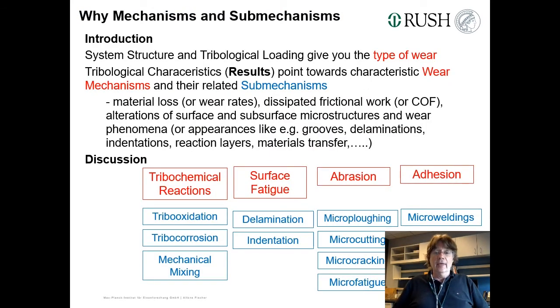Okay, so again, here are the four main mechanisms, and Zum Gahr introduced the sub-mechanisms for abrasion. Others did not really introduce sub-mechanisms, but if you read the literature of the last 70 years, you can take papers from the 1950s, 60s, 70s, 80s, and 90s, and after the millennium, and then locate them down here as sub-mechanisms of the four main mechanisms. Many people say that, okay, this is practical application, and this down here, this is science. It is not. Down here, at very small wear rates, you can optimize industrial tribological systems well aimed. You only have to do a little bit of analysis and a lot of thinking.